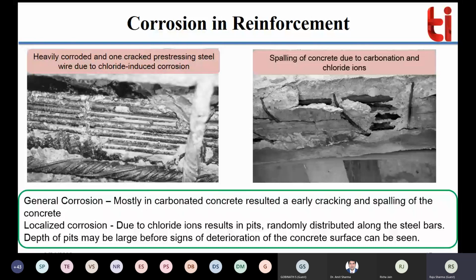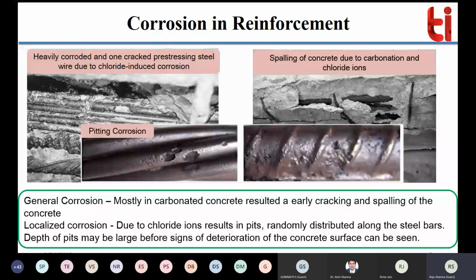If you see this in a larger image, you can see this pitting corrosion in the left side image, where this reinforcement is severely degraded because of the pitting, and this reinforcement is a pre-stressed wire. These are the pre-stressed tendons. In pre-stressed tendons, this cross-sectional area loss has happened because of pitting, and you know that this particular reinforcement is always under stress, right? It's always stressed. So the reduction in the cross-sectional area of reinforcement may result in brittle failure of the structure. Therefore, pitting corrosion must be avoided.